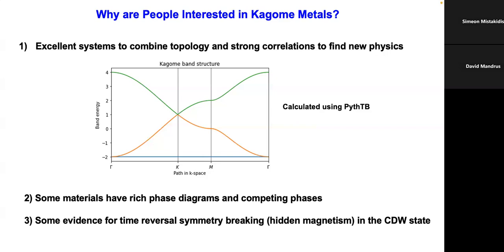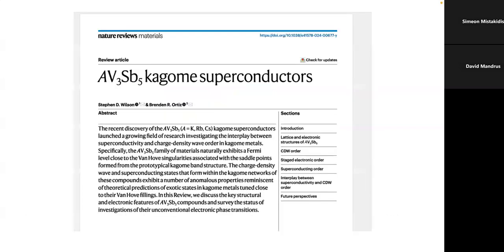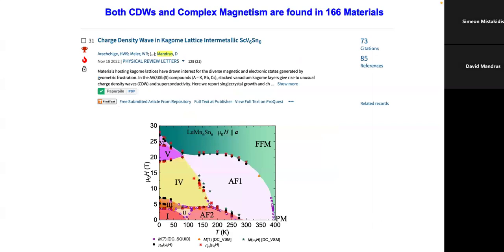A lot of these materials have rich phase diagrams and competing phases. There's been a lot of back and forth about whether time reversal symmetry is broken in what's called the charge density wave state. The system studied the most is the AV3Sb5 family, where A is potassium, rubidium, or cesium. They show superconductivity and two different kinds of charge density waves, and very complex phase diagrams. We've been studying a different class of materials, which are related, and we had a mini hit with this one. This is a double layer kagome, and we discovered a charge density wave in it, which got quite a bit of attention. We're also working on some magnetic materials that have very complex phase diagrams under magnetic field. That's the thinking, and that's why we started working in this area.